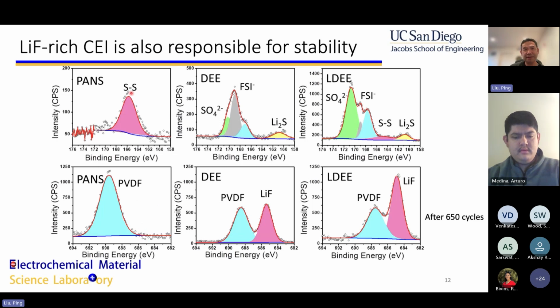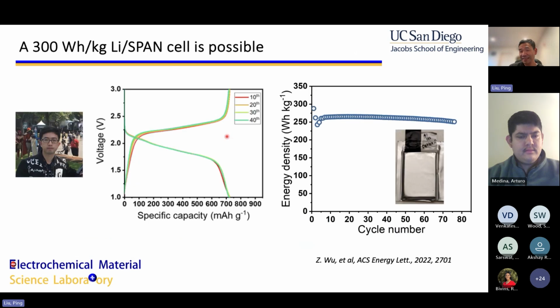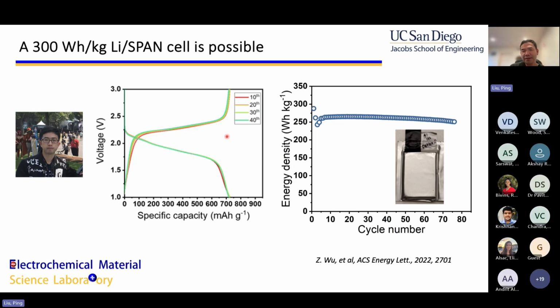If you look at this, this is a diluted ether electrolyte. In this particular case, you make less lithium fluoride, and the surface species are actually different, because here we make a lot of sulfate and here we make very little. And it's this type of species that forms a coating on the cathode surface that allows it to be reversible. So that's kind of what we did for a few years. We tried to discover new electrolytes, understand the chemistry at the interface, and then we actually made a real battery.